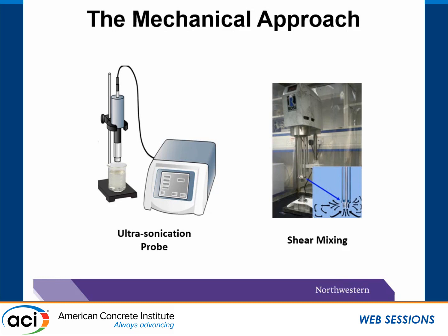The most used technique is ultrasonication energy. Dispersion through ultrasonication is the result of ultrasonic cavitation. The high intensity energy is passed through the medium and produces attenuated sound waves. These sound waves form ultrasonic cavitation in liquids, which causes high-speed liquid jets, and it applies mechanical stress on the attracting forces between the particles.